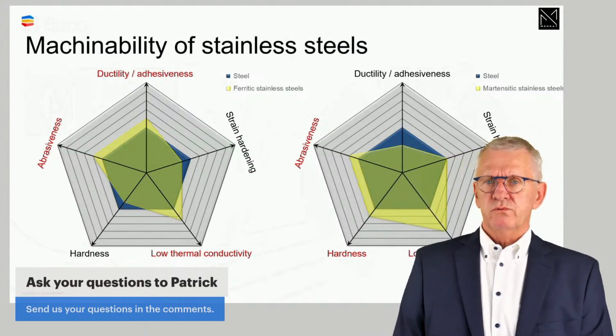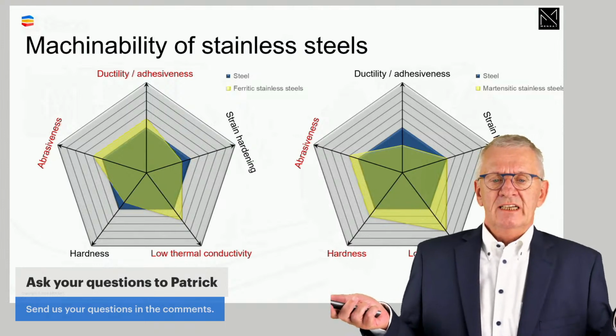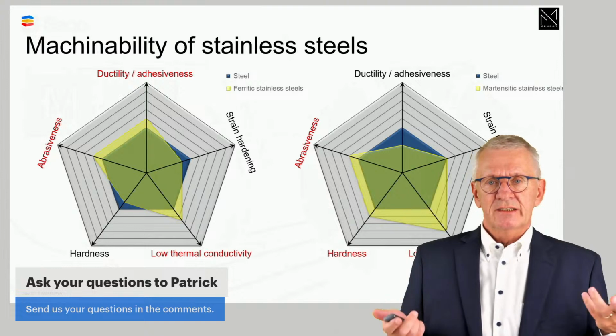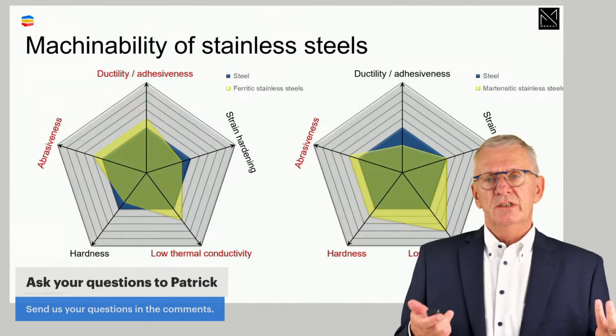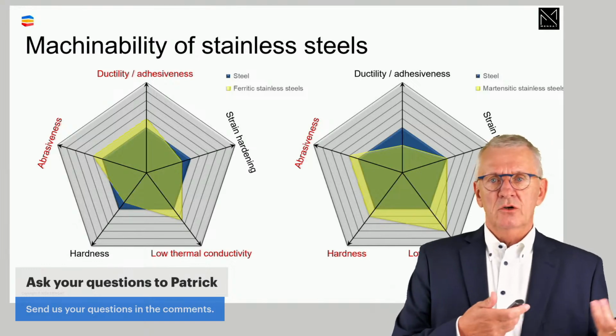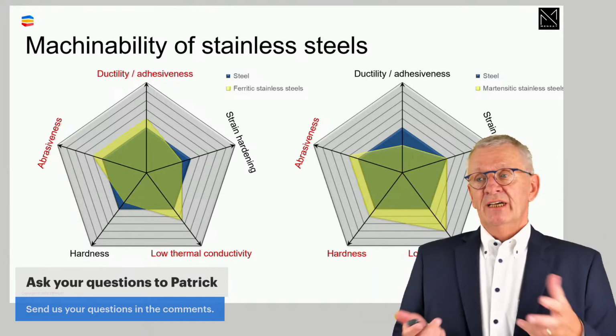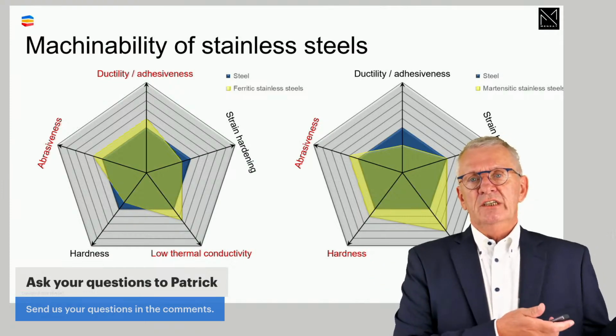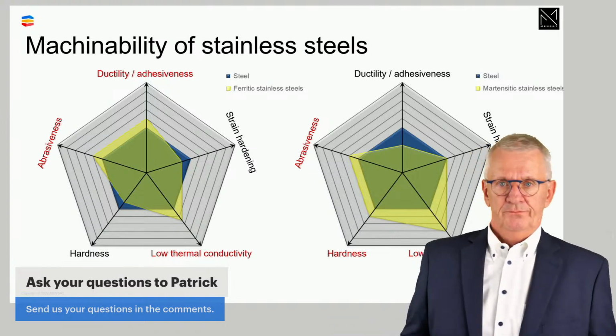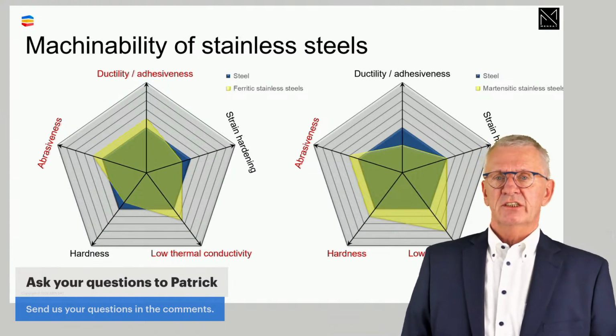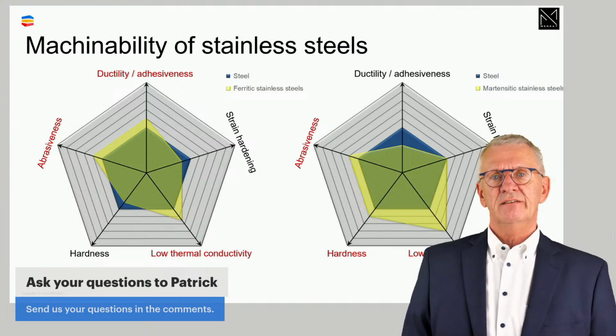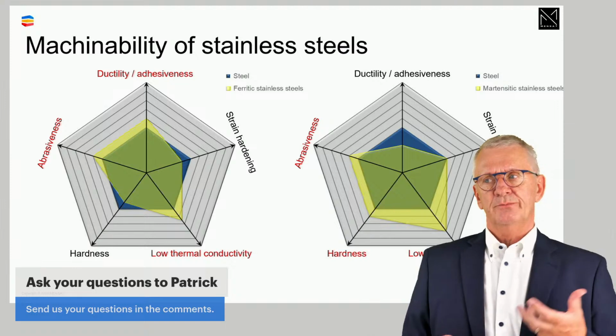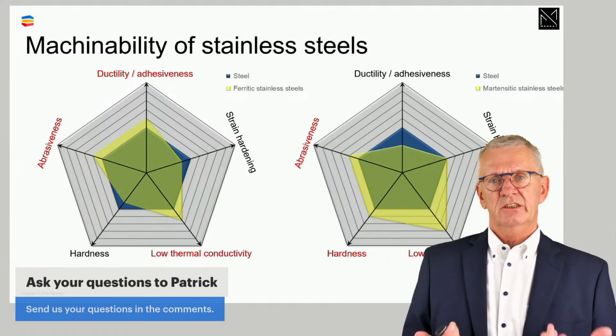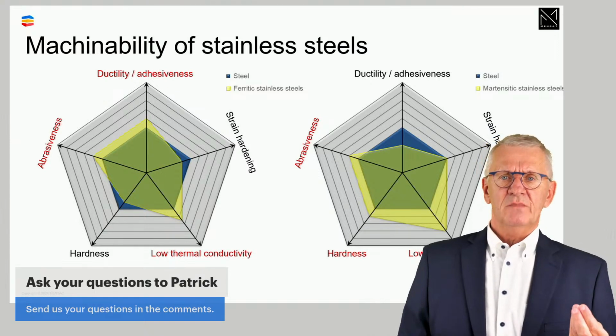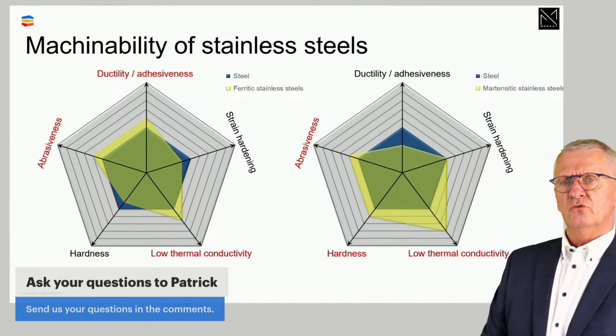It's nearly like steel. That's why there are some discussions that ferritic stainless steel should not be put in the ISO M group, but perhaps rather in the ISO P group. But I don't want to interfere with these. Ferritic stainless steel, whatever you know from steel machining, you can nearly copy it one-to-one. If you look at martensitic stainless steels, here you have, in general, I would say, a material which is a bit harder, a bit more abrasive than traditional steels. But you see that the thermal conductivity here starts to be lower, very much lower, compared to steel.